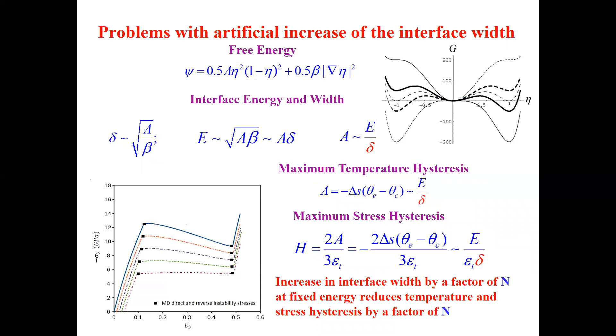That approach doesn't work for our goal because we study high-pressure phase transformations, which have huge hysteresis — pressure hysteresis, stress hysteresis, temperature hysteresis. For example, graphite to diamond: direct phase transition occurs at 70 GPa, and reverse phase transition does not occur at all. So it's huge hysteresis, and the key problem is nucleation — not growth, but nucleation — and we want to preserve it.